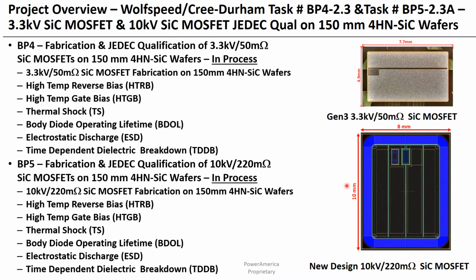To the right, you see the larger design of the 10 kilovolt, 220 milliohm silicon carbide MOSFET used in this project. These were all fabricated on 150 millimeter silicon carbide wafers. We are carrying out JEDEC qualification of these 10 kilovolt silicon carbide MOSFETs, including high temperature reverse bias, high temperature gate bias, thermal shock, body diode operating lifetime, electrostatic discharge, and time-dependent dielectric breakdown.